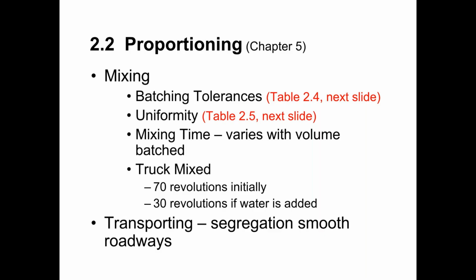And it's bobbing up and down because I'm watching that drum and I'm counting the drum revolutions. And so long as they remix the concrete a minimum of 30, that's acceptable and there are no issues, assuming that the truck is in good working order and that it's capable of actually remixing the concrete. If they do not mix the concrete a minimum of 30 drum revolutions after making an adjustment to the mix, then that would be a nonconformance for the audit.